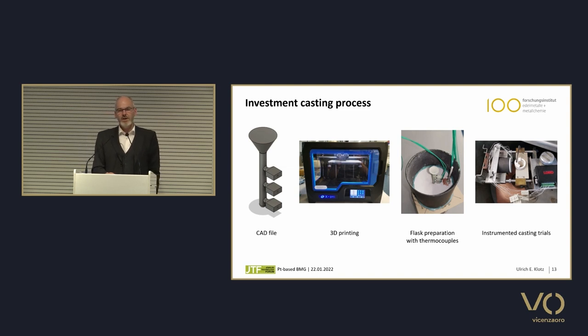Then for casting trials, we prepared some CAD files. We 3D printed the objects, and then we did the conventional investment process. We put some thermocouples inside the flask to monitor the temperature during the heat up of the flask, because we have to have a quite high cooling rate. And then we did some instrumented casting trials. We see the flask on the rotating arm of a centrifugal casting machine with the thermocouple wires going to a data logger, which is mounted on the arm. So during spinning, it can record the temperature profiles in the flask.